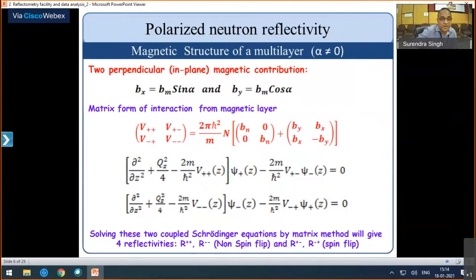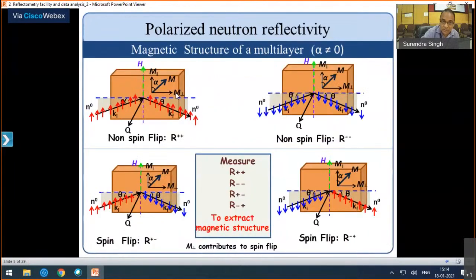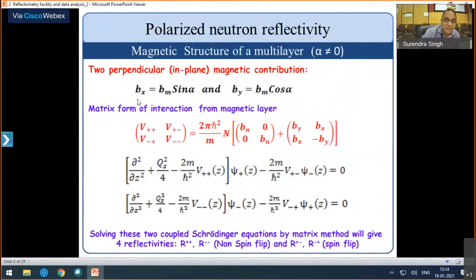So as we said, we have two perpendicular components. Bx is noted in the previous slide. If you see, I didn't show that xy - suppose this is x component, this h direction is y component. So the perpendicular direction is Bx, which is nothing but Bm sine alpha. If we say Bm is the scattering length, magnetic scattering length for the magnetic sample, and By is the cos alpha component, the parallel component.